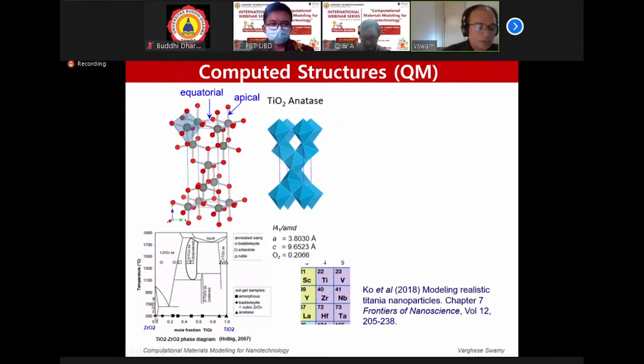But if you go to pure zirconium dioxide, it is the monoclinic phase that we have seen in the case of titanium dioxide at high pressure, and that is what is present. In between, if you try to mix these two materials without annealing or doing anything, you end up getting amorphous materials. If you heat the anatase TiO2 at some high temperature, it transforms to the rutile structure, which is the stable phase. Whereas the monoclinic zirconia eventually becomes tetragonal zirconia and then melts. So you can see that they are different structures.